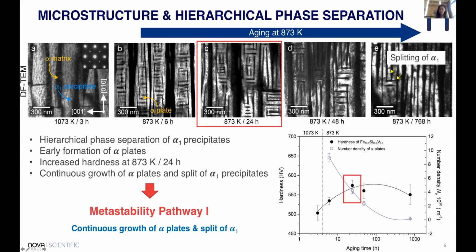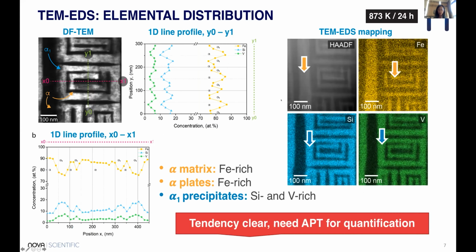To get an idea of the general distribution of alloying elements, we perform TEM EDS analysis. Here, we focus on a smaller area showing some alpha matrix, alpha-1 precipitates with alpha plates inside. We measured the concentration along two lines across all phases, from X0 to X1 and from Y0 to Y1. The profile clearly reveals that the alpha matrix and plate phases contain more iron than the alpha-1 phase, and that in turn, the alpha-1 precipitate phase contains more silicon and vanadium. The HAADF image and the element mappings on the right side show this trend very clearly. So the tendency is clear, but we need atom probe for a detailed quantification of these small structures.